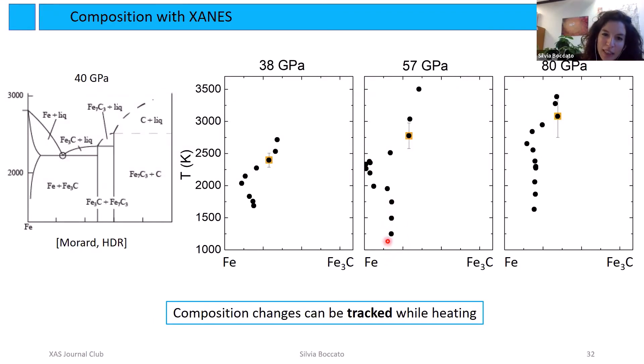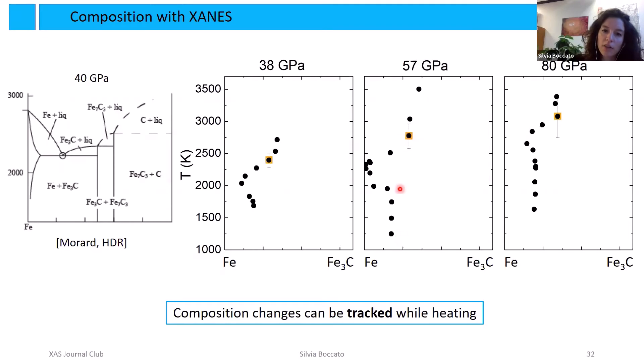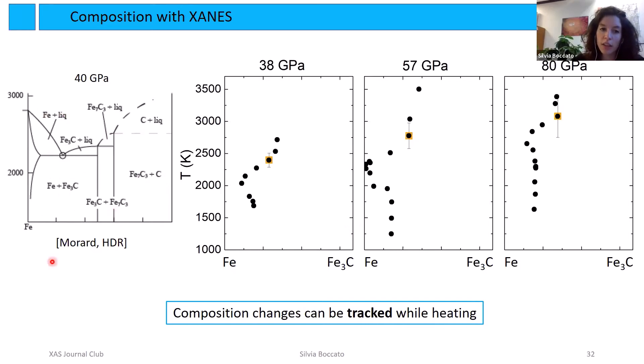We see that we started with a starting composition of about 1.5% carbon. While heating, carbon goes into solid solution with iron and disappears. Heating further to the eutectic point, we reach the eutectic temperature and eutectic composition. If we overheat, the composition no longer changes. Using the same measurement, we can probe the chemical phase diagram as a function of pressure. The results on melting curves and composition analysis have planetary implications — this work is ongoing.